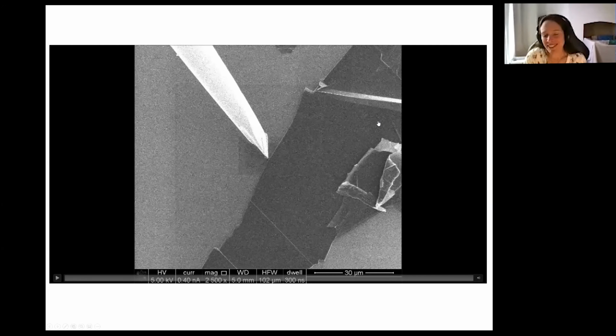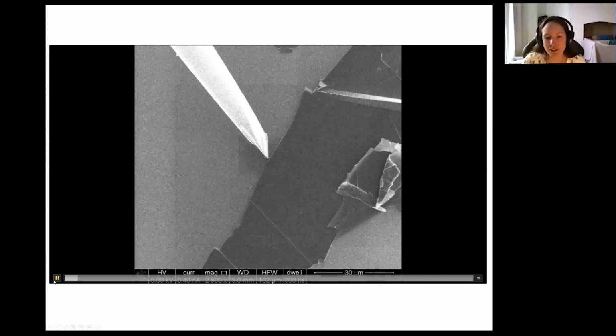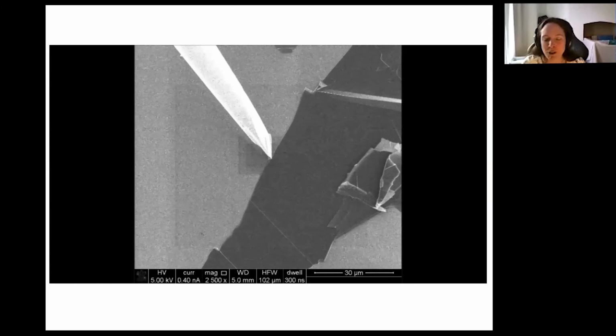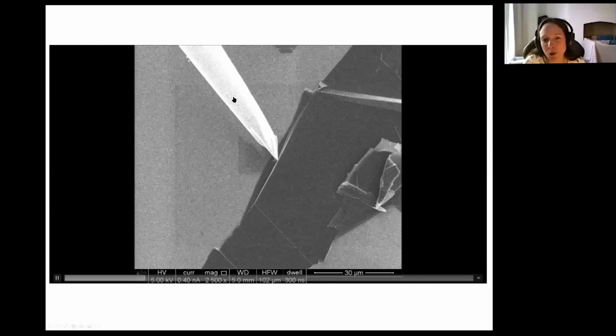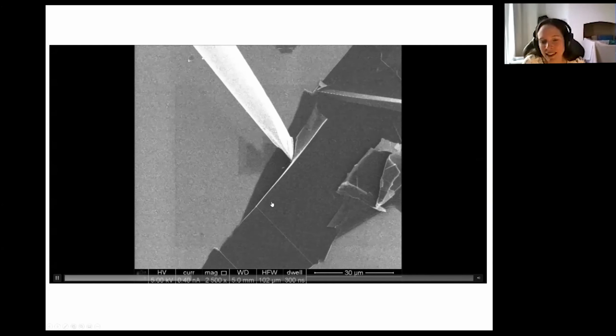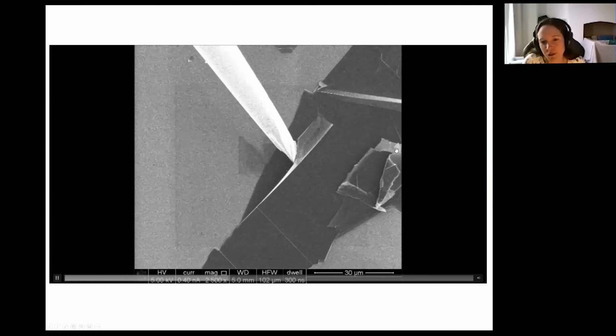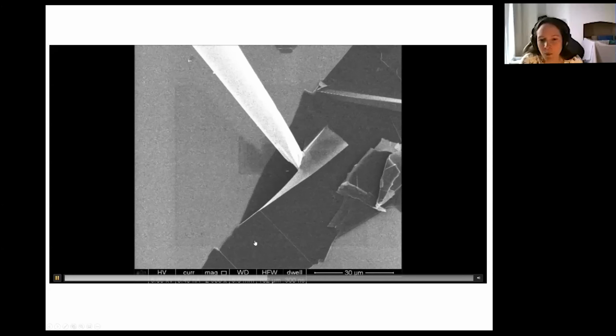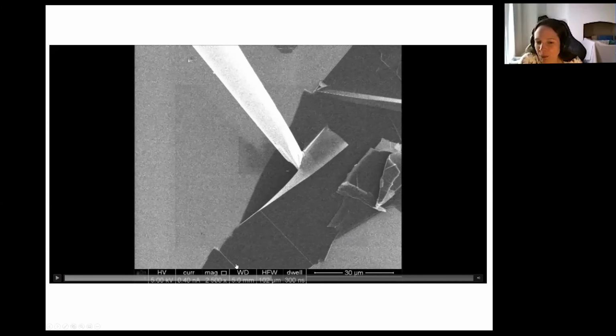Okay, great. So now this is a scanning electron microscope image, and it's actually a video which Aidan Rooney took in our focused ion beam. The focused ion beam has a micromanipulator system. So what we're looking at here is him using the micromanipulator to try to simulate exfoliation of this piece of graphite here. I'm going to pause it here because what I wanted to draw your attention to are these lines that we see on the surface of this exfoliated flake. These lines have typical crystallographic orientation, so they're orientated with respect to the crystallography of the specimen, and you see them at orientations compared to each other of 30 degrees. But we'll see how they happen a bit later.